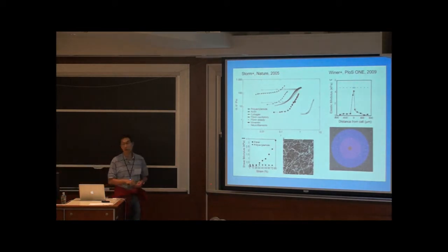It turns out that all biological materials are not linear. So here's a graph of this stress strain done by Paul Janmey many years ago, where he looked at all the different types of biological polymers. So I don't know if you can read this, but there's actin, collagen, fibrin, and in all cases what you see is that the modulus changes with how much you strain it. So that means it's nonlinear, right? It strain stiffens. So it's shown, for example, here, this is the fibrin curve, and this is the collagen curve. So you can see they're highly nonlinear.